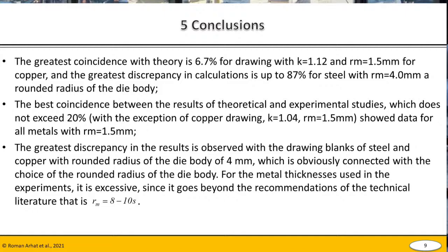die body. For the metal thickness used in the experiments, it goes beyond the recommendation of the technical literature, which is around 8, 10. This pattern does not reflect the analytical relationship, but gives a more accurate match of the data. Therefore, the completion of the dependencies is obvious, but in the existing format, it can be used for calculation of the drawing process with the rational geometry of the tool.